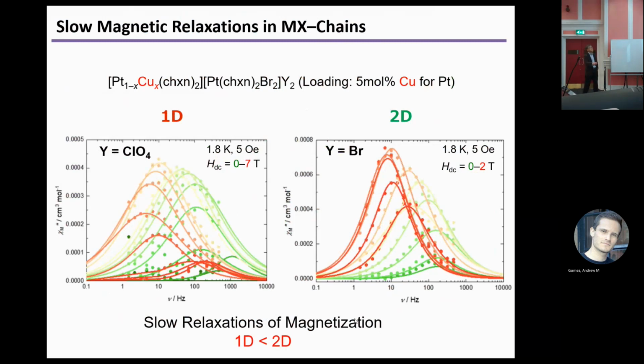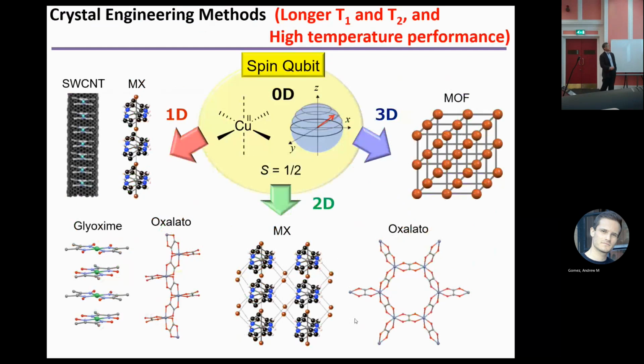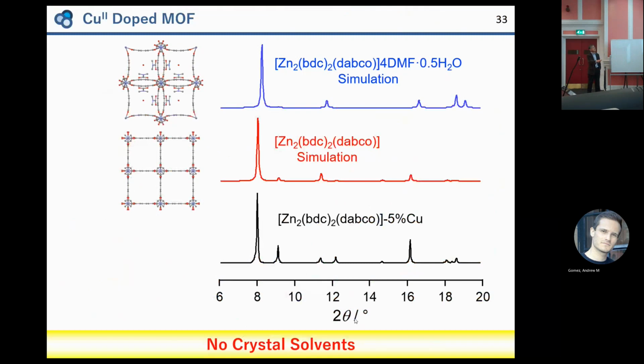And we dope into the three-dimensional MOF. I don't like a MOF, but I use a MOF. So in the zinc MOF, this diamagnetic species, we doped 5% of copper in the zinc. The powder pattern shows the same structure, so copper 5% was successfully doped.